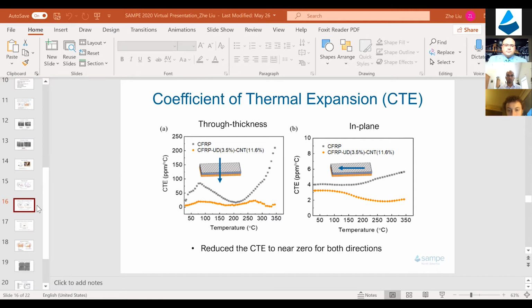And with our carbon nanotube shielding layer, we can see from the figure, left is the through-thickness CTE and right is in-plane. For both directions, we can reduce the CTE to almost around 0. That means we have a very good bonding between the shielding layer and the composite, and it also limits the expansion space of the polymer chain.